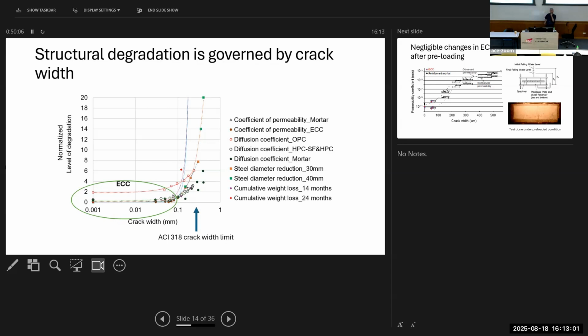Okay, so we were surprised by ourselves. This is a nonlinear process. Degradation simply accelerates nonlinearly as the width of cracks increases. And especially that there is an elbow point here at about 100 microns. So obviously for us, we want to keep our cracks intrinsically tight to less than 100 micron, let's say 50 micron or less in this region. That's what we aim at for ECC. So ECC has naturally tight crack width that do not require external intervention. You don't want to close the crack. You can't do that on a bridge deck. Every time there's a crack, you try to close it. You want it to be intrinsically tight, allowing very little or zero degradation.